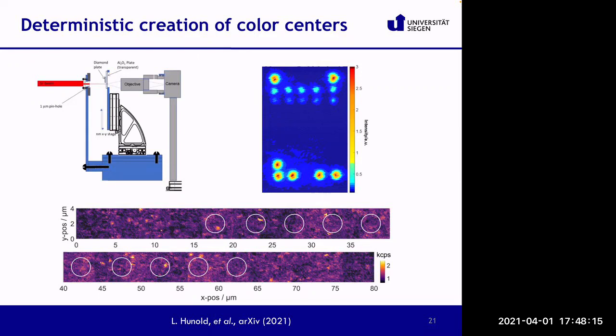the activity on electroluminescence. Now I want to talk a little bit about one problem, which is the deterministic creation of color centers. Of course, when you do the implantation, you don't know where your ions go. So, in principle, you create a single photon source somewhere in your sample, and then you have to look for it with your microscope. This is certainly not ideal if you want to make devices. And so, we also investigated, like many other groups, how you can create these color centers at the desired position with a kind of deterministic approach.